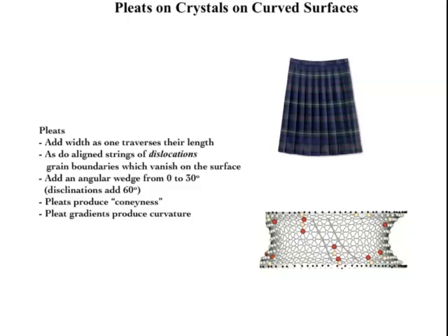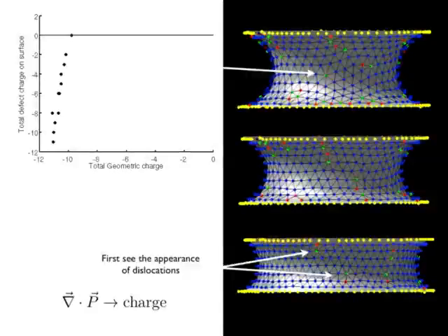That's a shame. What we discovered, again, about 5 millennia too late, okay, was pleats. Because a pleat is something you do if you take a fabric and your waist is smaller than your hips, and you want to add material as you go down. So if you add material as you go down, that's like having a dislocation, which as you add dislocations, you're adding material as you go down, right? And so these guys are pleats. They're the equivalent to pleats, okay? Like that, okay?